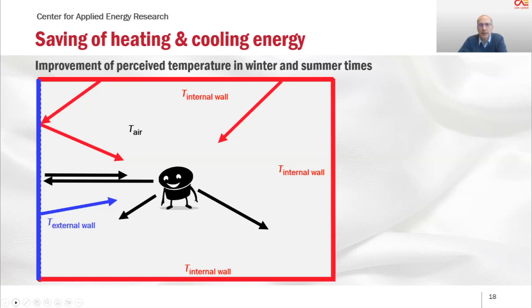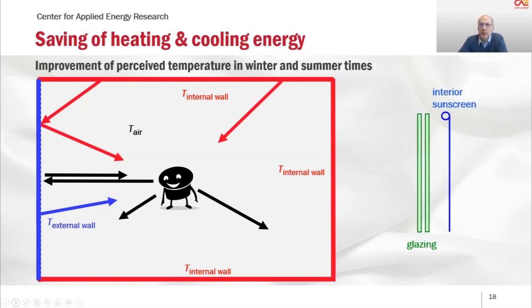Here, for example, so next please, you see an interior sunscreen behind the glazing, and during summertime the solar radiation goes through the window or the glazing and heats up the internal sunscreen, and then the sunscreen emits thermal radiation into the room, and during summer times this reduces the thermal comfort. But by applying a low E coating on the internal sunscreen, you can reduce the thermal radiation emitted into the room and therefore increase the thermal comfort also in summer times.